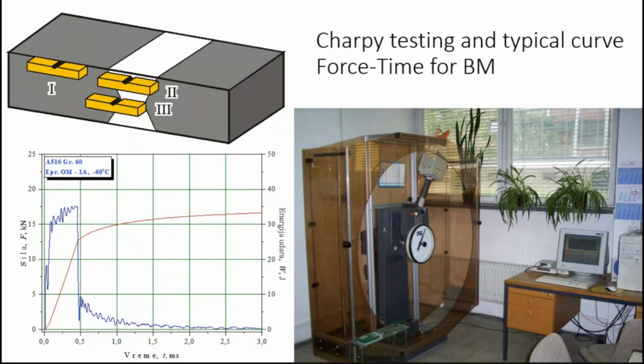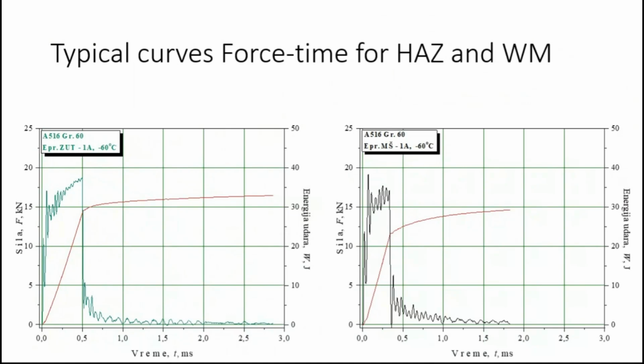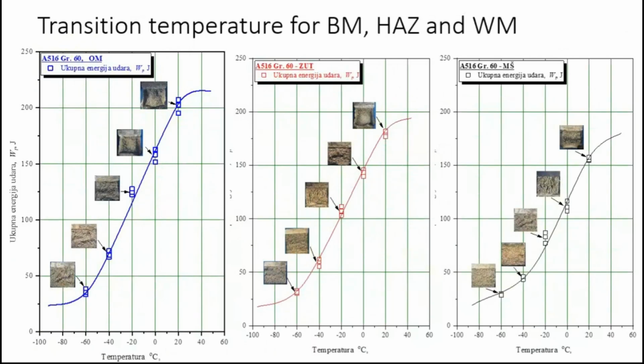So, in any case, we did testing, as I just explained, and obtained typical curves of force versus time for the heat-affected zone, for weld metals, for base metal, and some of them, as typically obtained, are shown here at -60. Focus was here on -60, and on getting the temperature dependence of total energy versus temperature. So here we have, as our final result, base metal, heat-affected zone, and weld metal. You can see at once that it's quite similar. In my experience, which is a big one, differences are usually bigger than this. So this steel behaves nicely in a sense of its welded joints.